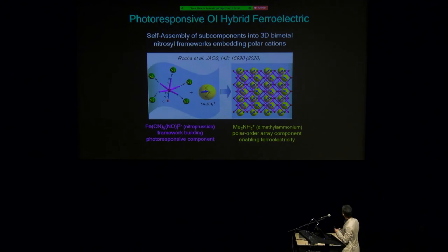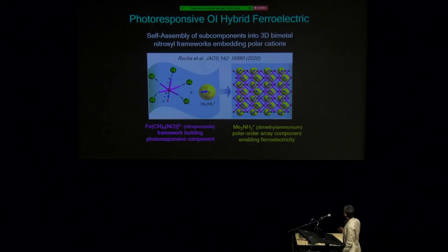Now I keep on talking about hybrid materials. I slightly changed the topic. This is much more recent work. We are now interested in ferroelectric materials, but hybrid, organic and inorganic ferroelectric materials, which can also be photoresponsive. So basically what we did, we self-assembled two types of components. On one hand, a framework building component, which is also photoresponsive, and that's the very well-known nitroprusside ion. And in order to get polar order, we added some organic polar cations, such as dimethyl ammonium cation. And by self-assembly, we get a structure which is ferroelectric at room temperature.